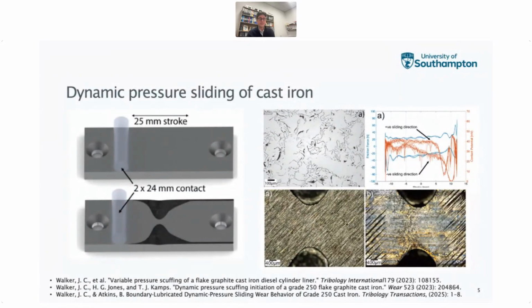So that's quite interesting, and you can also see there's differences in the wear behavior between before we do the test with the ground surface here, and actually where you do have a higher contact pressure, you're getting differences in how that material is removed from that particular portion of the contact, and that's quite interesting. That means we can do all of this in a single test and not have to repeat multiple tests to change the conditions parametrically. So it's a little bit more efficient with the testing resources as well.